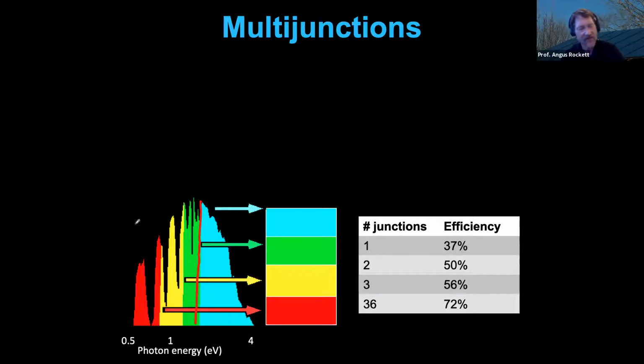So we get a lot of energy out of the blue part of the spectrum, but we don't get much current. And so if we move our junction down to a lower energy, we get more current, but we lose voltage. The ideal semiconductor band gap is around 1.4 electron volts, but that has limitations, and silicon is much too low.